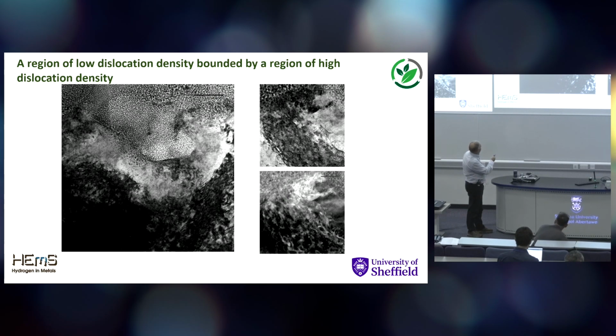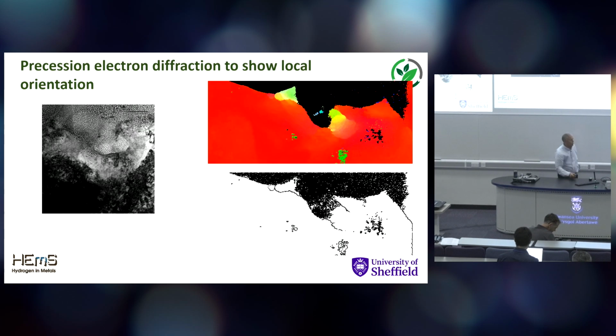We've got this region around here, the light region, which has very low dislocation density, and then quite an abrupt subgrain boundary that goes around here with a region of very high dislocation density next to it. Really rather odd, we hadn't seen anything like this before.